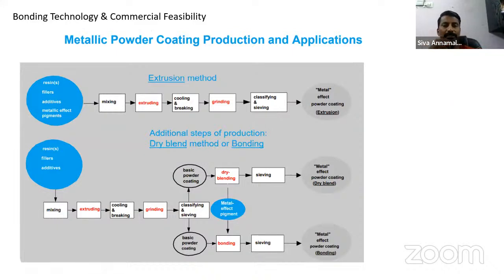So, second one is metallic powder coating. We all know how powder coating is manufactured. Once we manufacture powder, to get metallic effect, there are three methods currently available. One is the extrusion grade product. It means you make powder coating: premixing, extrusion, milling. In that, at the time of premixing, you add certain kinds of metallic pigments into the premixer, then you extrude it, then you mill it, and you supply. This is called extrudable grade metallic powder coating.